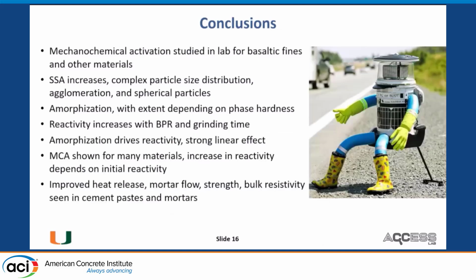So with that, I'd like to conclude. We studied MCA in the lab for basaltic fines and other materials. The physical changes are really quite complex. There seems to be a trimodal sort of particle size distribution generated, agglomeration, and spherical particles. But for the reactivity, I almost feel like this does not matter all that much. But the amorphization, where the extent depends on phase hardness, seems to control the reactivity. But the spherical particles generated seem to be improving the workability, a work in progress again.